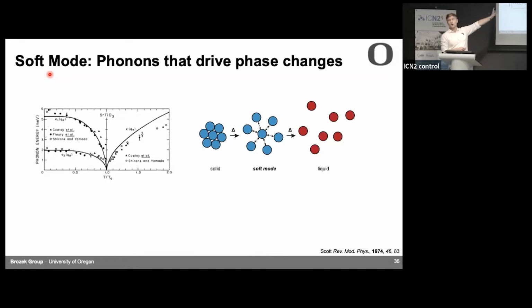So for example, in the perovskite strontium titanate, you can follow some of the vibrations, and you heat up the material, and those vibrations will redshift until they go to 0 at the phase change temperature, and then you keep heating, and they move into a new vibration. So it turns out a lot of phase changes are triggered by a vibration. In fact, when something melts like ice, there's typically a vibration in ice that is causing the water molecules to change so much that it causes the ice to melt. So it turns out it's actually a very general phenomenon. And if there's a vibration that does it, it's called a soft mode. That's what I'm showing in this cartoon here.